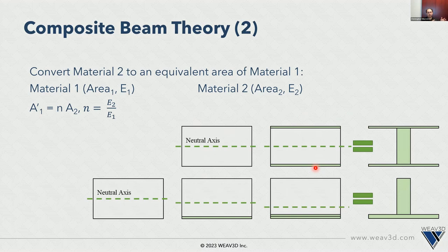I convert the original material into an equivalent area of the composite material, and my equivalent area looks like an I-beam. If I then take that neutral axis and apply that material only to one side, with the same number of layers, so 2 layers to one side, you'll notice the neutral axis comes down, which means that it's less efficient to add material to one side versus both sides, but your equivalent cross-section is a T-beam.